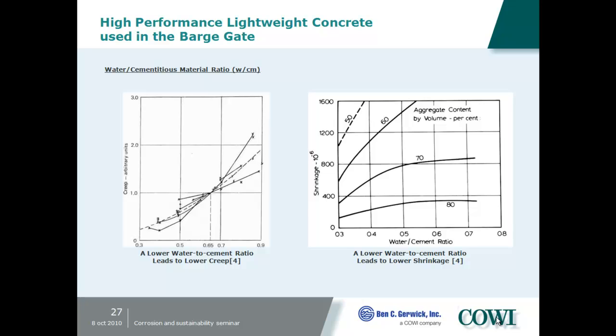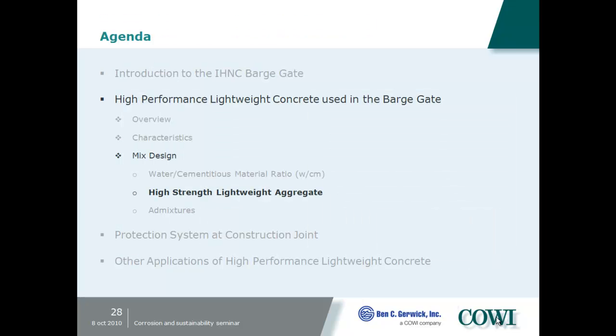So here's other influence on creep. As your water cement ratio goes up, your creep goes up, so that's something you want to control. And you also want to get a good amount of aggregates in there to reduce shrinkage. But also the low water cement ratio reduces shrinkage as well.